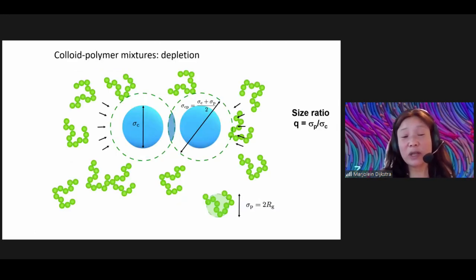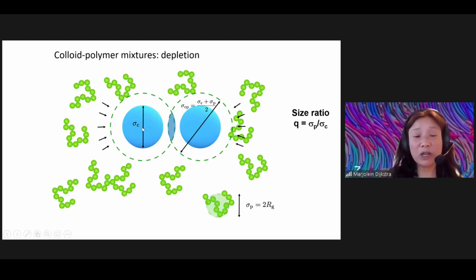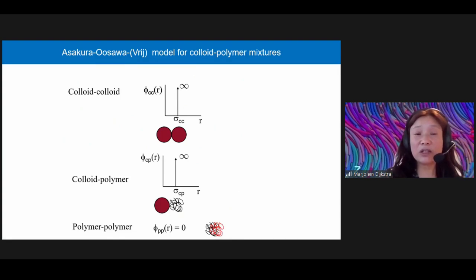And so if you have a colloidal suspension, and I treat the colloidal particles here as hard spheres, you can add non-adsorbing polymers, and that induces basically effective interactions between the colloidal particles due to an unbalanced osmotic pressure, where the polymers can only push from the outside onto the surface of these colloidal particles when the colloidal particles are so close to each other that none of the polymer coils can fit in between the colloids.